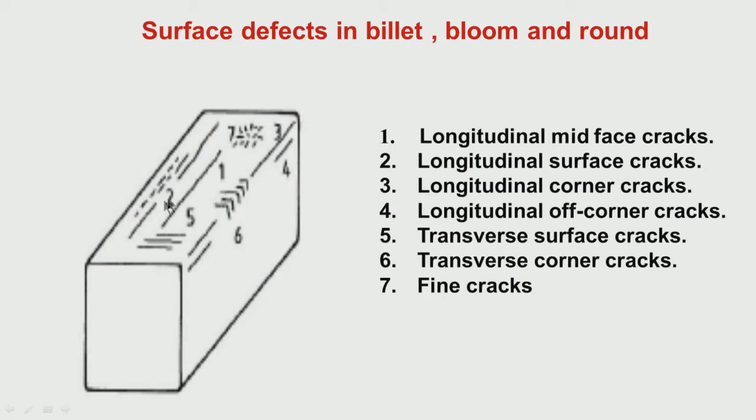See, the first one, these are longitudinal mid face cracks. What is the location of the crack? It is longitudinal because it is in the casting direction, the long direction. But the location is mid face. This is one face, which we call a broad face. So, here at the mid region of the face, if you have a crack, we call it a longitudinal mid face crack.